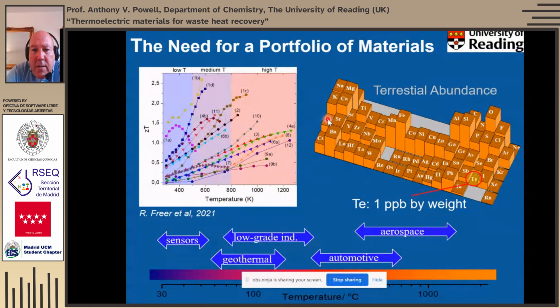A further constraint that we have is really on the actual component elements themselves. So most high performance thermoelectrics to date, including bismuth telluride, have appreciable quantities of tellurium in them. So bismuth telluride down at ambient type temperatures, lead telluride at higher temperatures. The abundance of tellurium in the Earth's crust is about 1 part per billion, which is about the same as